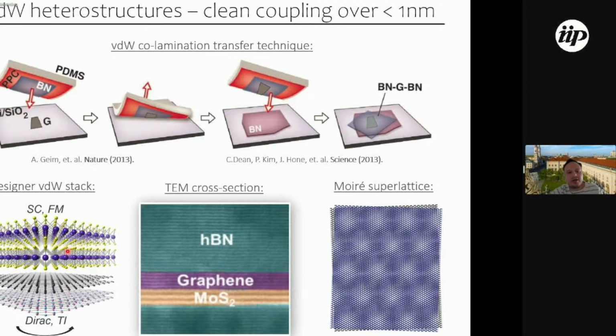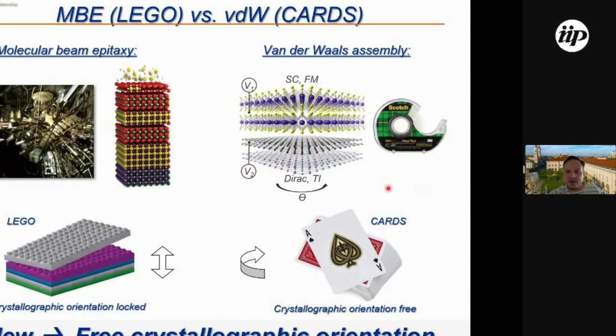And not only can you assemble these materials this way, but they also show very nice quality. If you take a transmission electron microscopy image and look at the quality of the interfaces between these layers, you find rather clean interfaces, and regions which are perfectly clean and hybridized, which then allows us to observe this rich physics. One thing I also want to emphasize is that the principle of creating a Moiré superlattice relies on this technique, because by starting assembly from the platform of 2D materials, we can change the orientation between these materials as we like, and therefore create these Moiré superlattices.